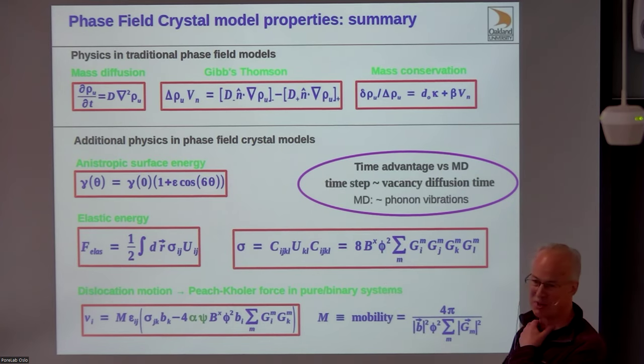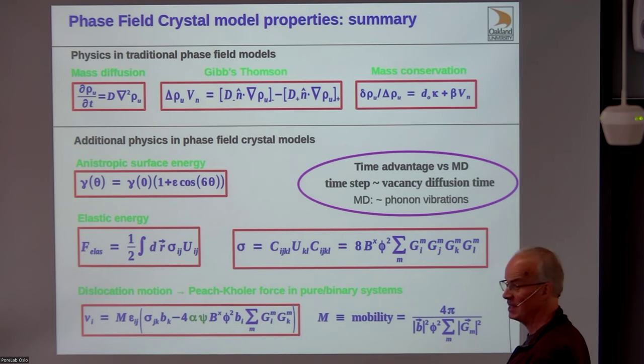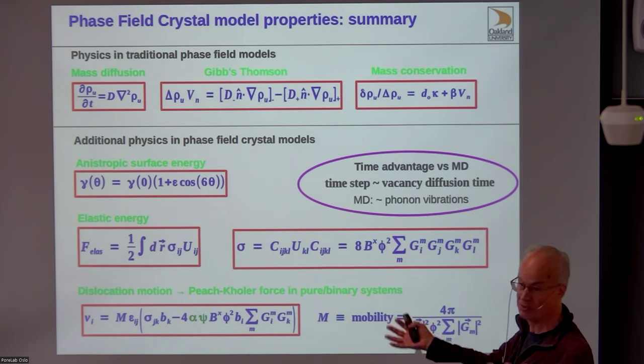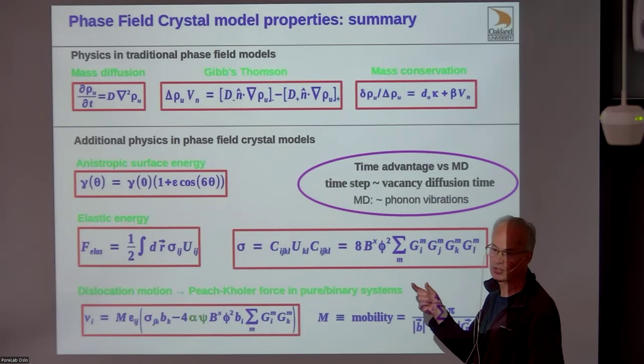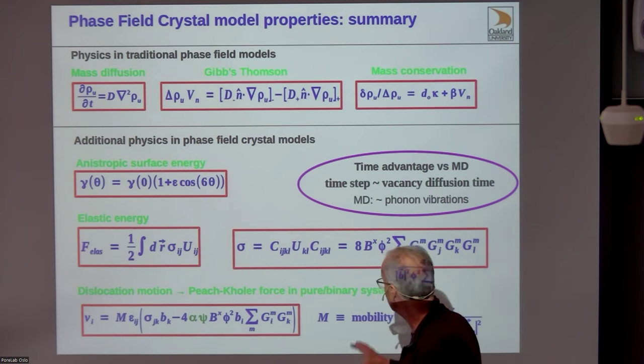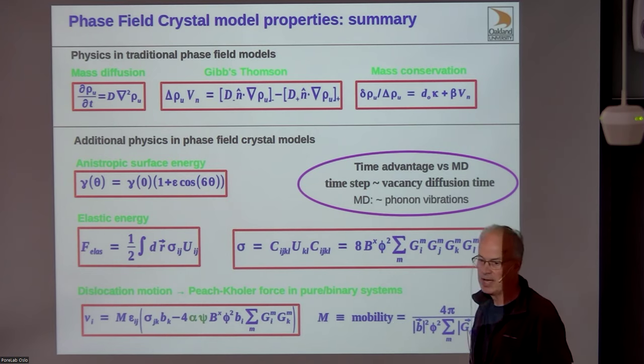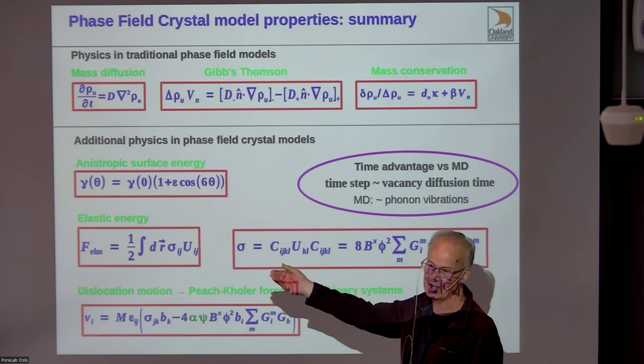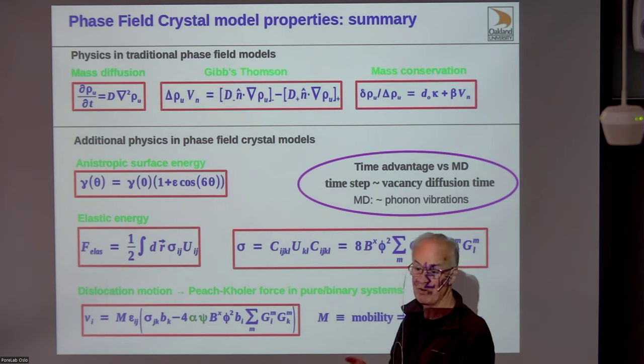The reason you do PFC rather than molecular dynamics is that in MD your time step is limited by lattice vibrations—picoseconds or femtoseconds. In these phase field crystal models, your time step is limited by the vacancy diffusion rate, which can vary enormously from seconds to nanoseconds. Typically, in many cases the time step is about a million times bigger than in MD, sometimes ten million times. In some cases they can be quite similar, depending on the diffusion constant. That is the advantage of this approach.